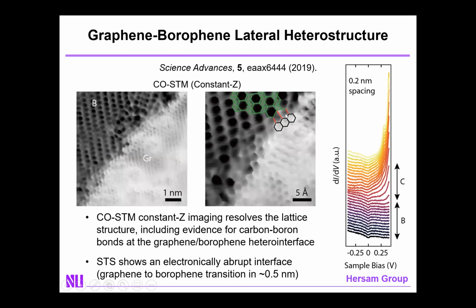It really has a hard time satisfying the octet rule and will contort itself in all sorts of unusual geometries in order to do its best to achieve that condition. In addition, we can use methods like scanning tunneling spectroscopy to look at the electronic density of states across the heterointerface. And as you may expect from this relatively abrupt atomic structure transition, you also see a relatively abrupt electronic transition, wherein you go from graphene to borophene electronic structure over the length scale of about 0.5 nanometers.